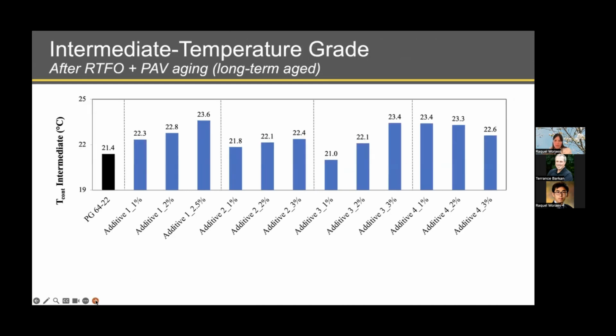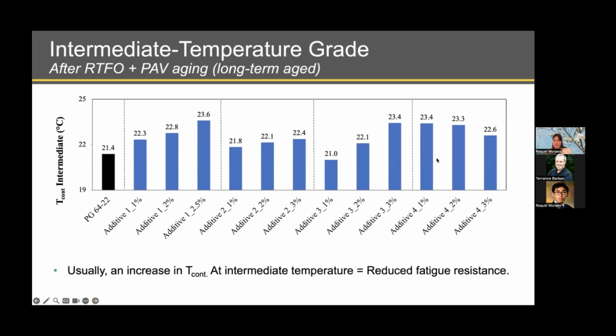Then we evaluated the properties at intermediate temperature after the binders were aged in the RTFO and PAV. You can see here in black the base binder and in blue the graphene modified binder. For this specific test, we wanted the pass-fail temperature to decrease, in terms of improving the properties of the base binder. We can see that all of the graphene modified binders show a pass-fail temperature higher than the base binder, with the exception of graphene additive 3 at 1%. However, the change was not very significant. It means that the overall contribution of the additives was not so detrimental.